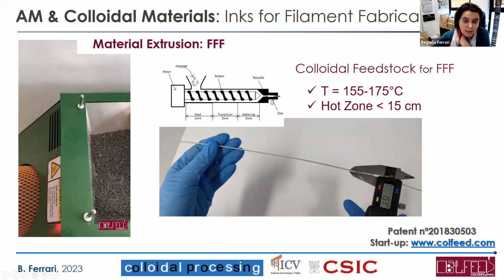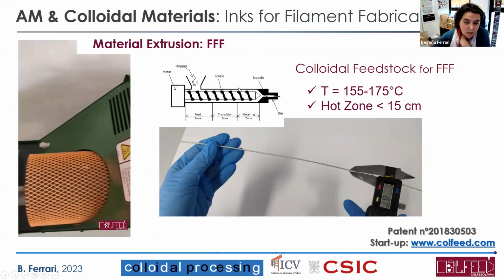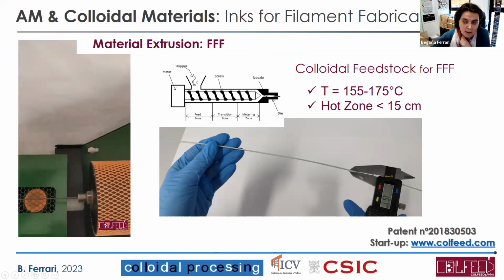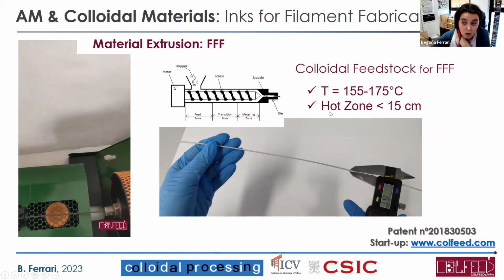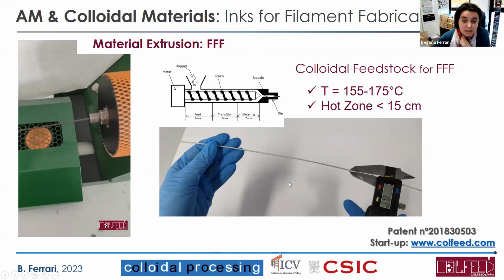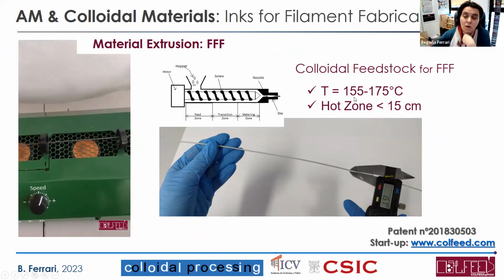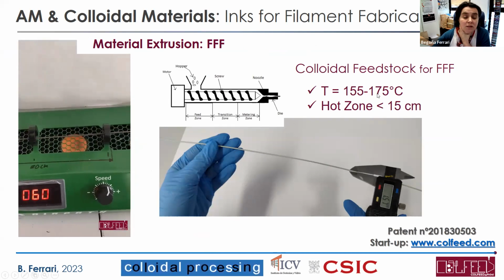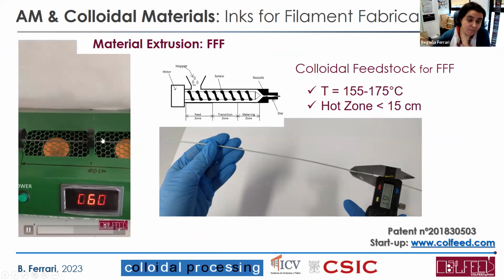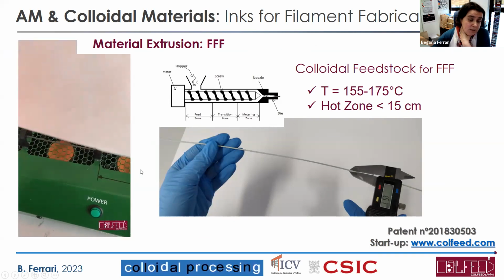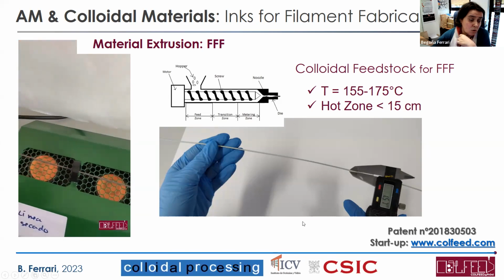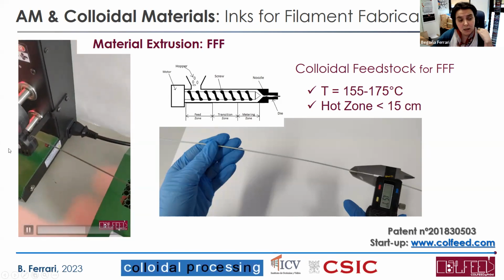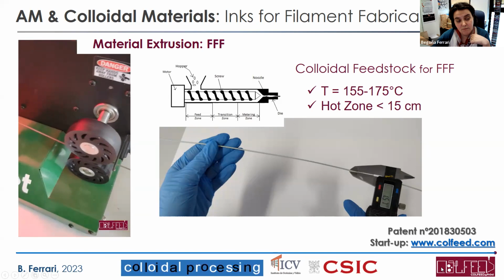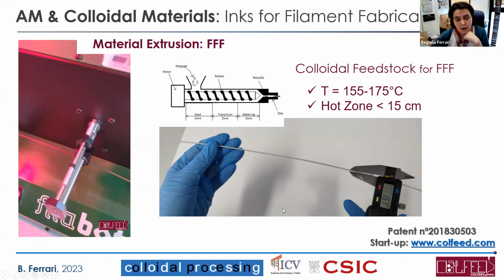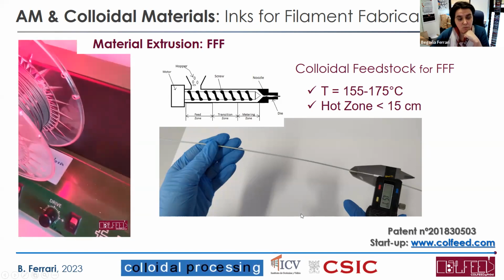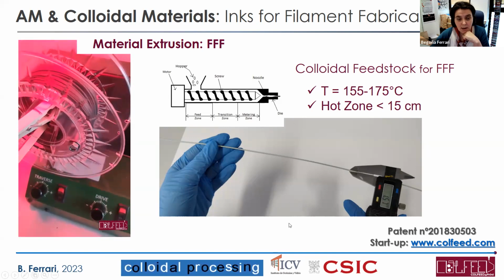We are using a very small extruder with only 15 centimeters of hot zone, and extrusion temperatures in this case of around 150 to 170. And you see here how we can extrude our material or granules, and how we can create the filament and spool it. So this is the way that we work in the company.